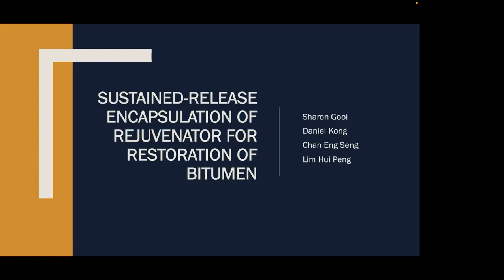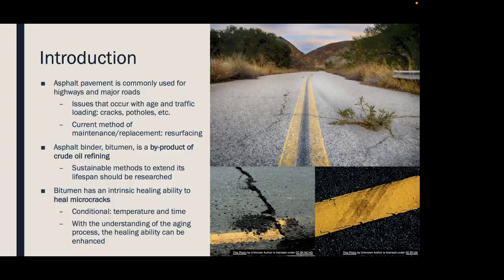Okay, so the focus here is on the encapsulation process. Just some introduction for those of you who are not familiar with the asphaltic pavement area. Asphaltic binder over time does crack because of the changes of temperature. So one of the ways to address this is to introduce some healing agents in the form of oils, and once it's introduced at the correct timing, it does enable the material to self-heal. Okay, but the problem is, how do we then embed it into the matrix?